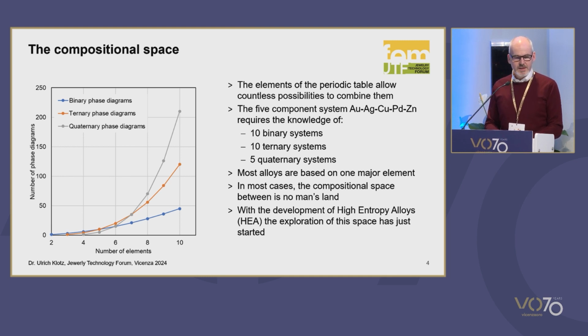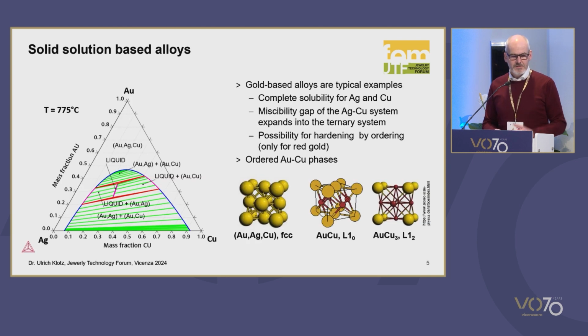needs to be explored. And there is a very interesting development going on at the moment, so-called high entropy alloys. This is a special class of alloys where all elements are mixed in a similar range. So 5 elements and every element around 20%. It was found for steels or other aluminum containing alloys that such alloys give very interesting properties that are different from conventional alloys. So knowing all these systems experimentally is extremely hard work and very difficult to solve. And therefore, we need some screening approaches, which I will talk about.